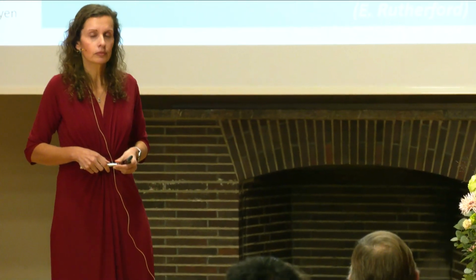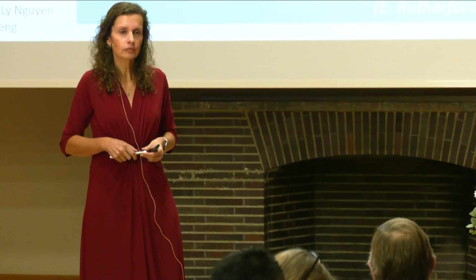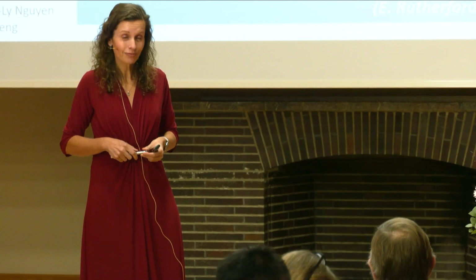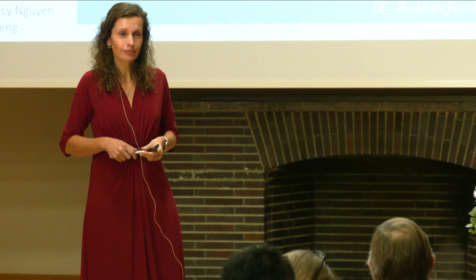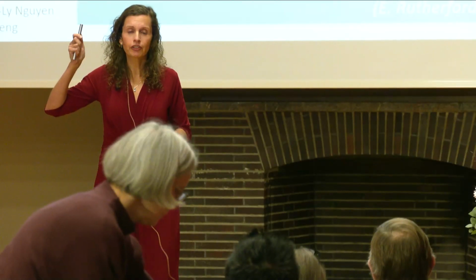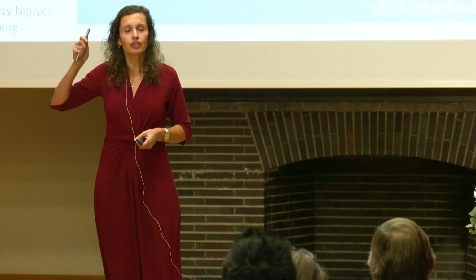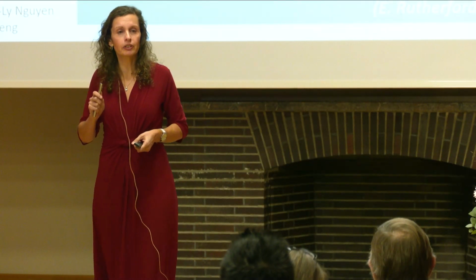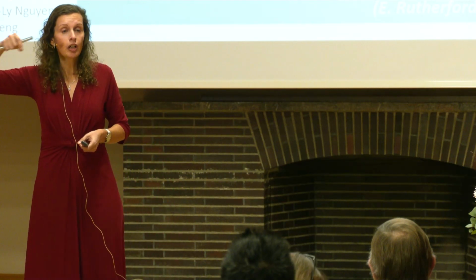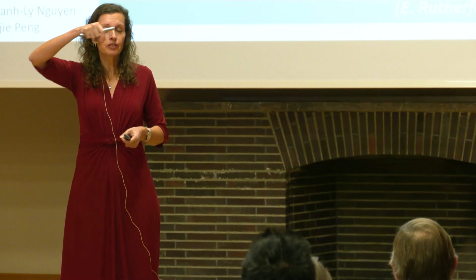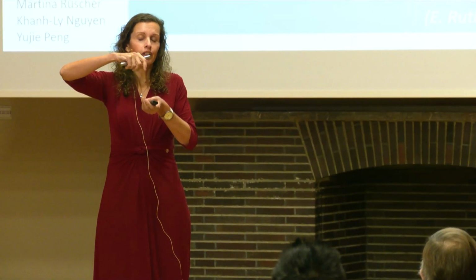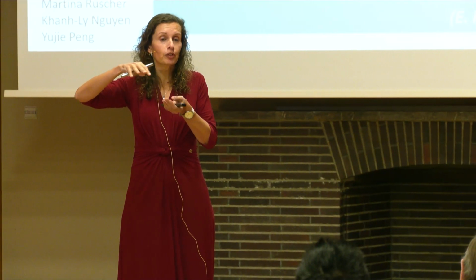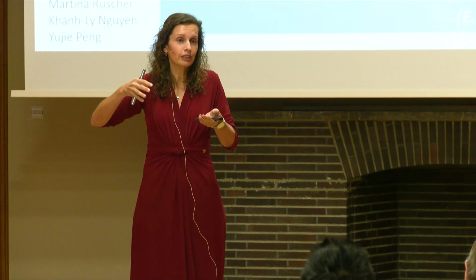So you mentioned faceting and surface termination. Do you know which are the facets that might be most effective? You saw the example here for this cobalt oxide species, this 100 seems to be much better. Again, you see changes, but on the 100 surface, the structure of the highly disordered oxyhydroxide that forms seems to be more active.